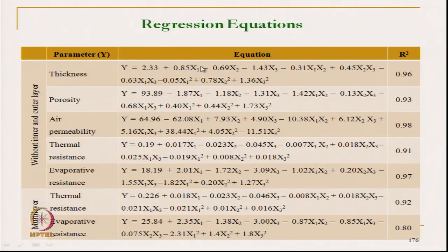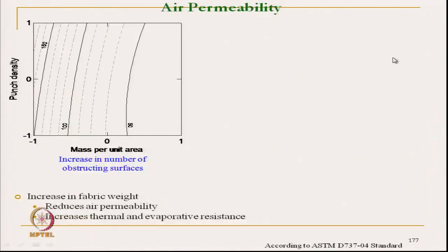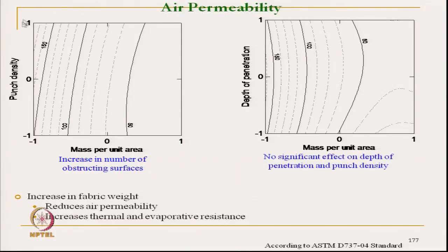So, here is the regression analysis without any outer layer. Without any inner and outer layer, it is only the middle layer here. If we see the coefficient of regression, it is a very high correlation for most of the parameters: the thickness, porosity, air permeability, thermal resistance and evaporative resistance are well correlated with all these experimental parameters. So, if we see here in this contour plot, the increase in number of